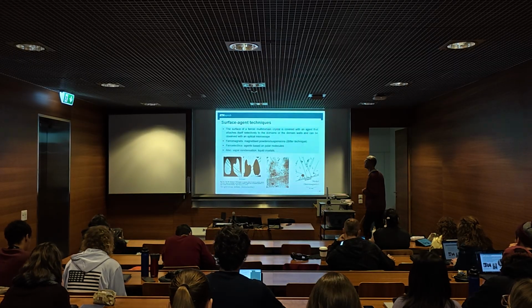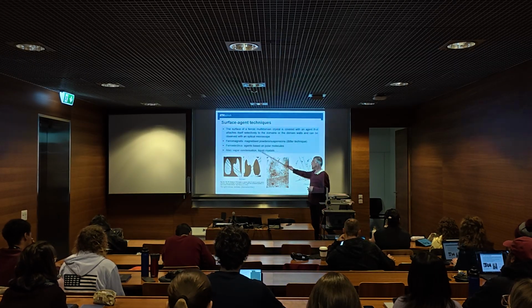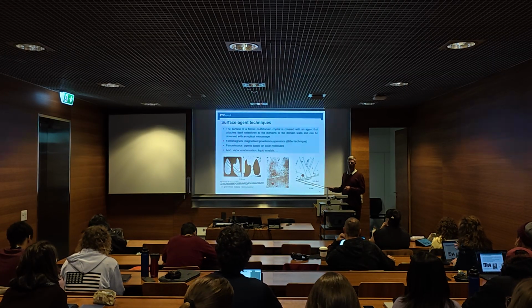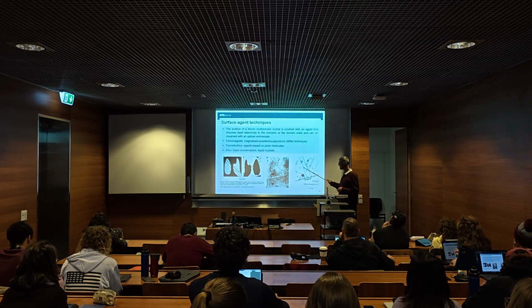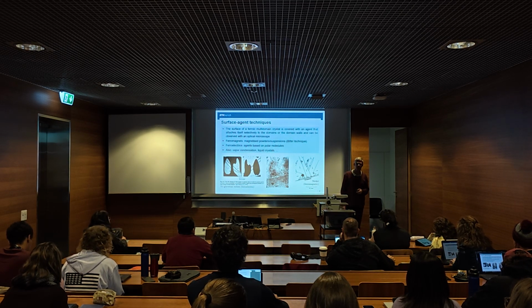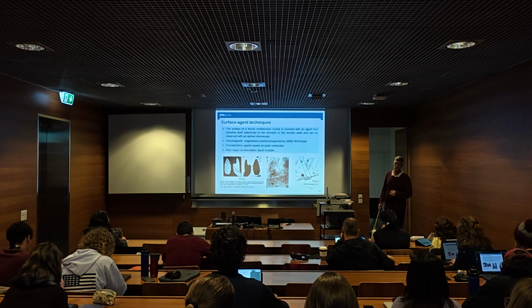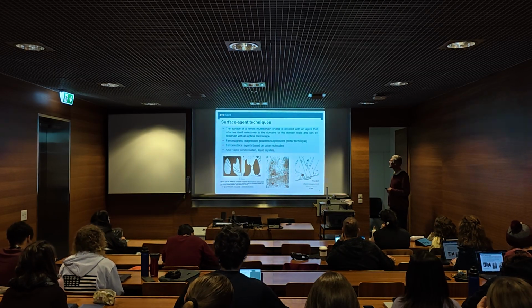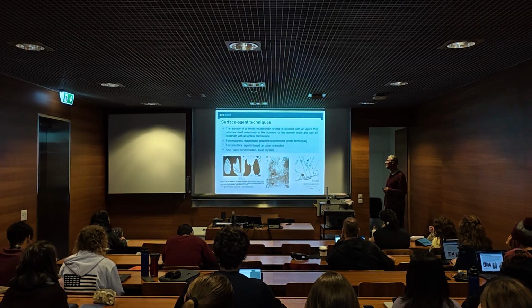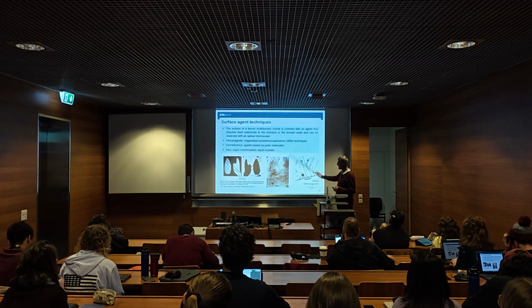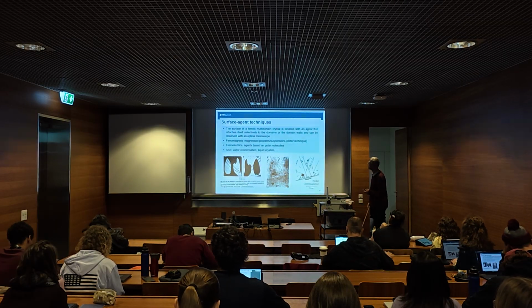Well, you can also use vapor condensation. If you have an oversaturated atmosphere, then certain inhomogeneities attract condensation, and you can see the distribution of domains from that. So there are several ways to do this. Again, it's not very convenient, and is still basically of historic value. The name for this for ferromagnets is the Bitter technique.